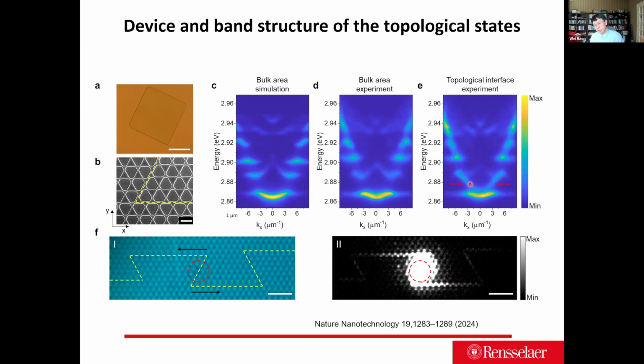So once you pump, you have a little blue shift. You still condensate in that region. So we selectively tune the samples so that the topological edge is in the region that a typical unpatterned sample likes to condensate in. We make that our topological gap region so that eventually they will condensate in that region. I think the same thing for gallium arsenide, right? They have certain spectral region where they like to condensate, and you make the sample's topological edge in that region by changing the detuning of it. So essentially, the detuning is the relative position of the exciton and photon.